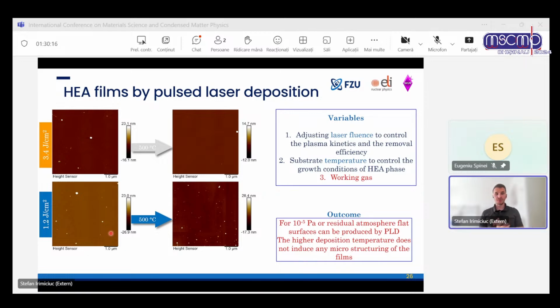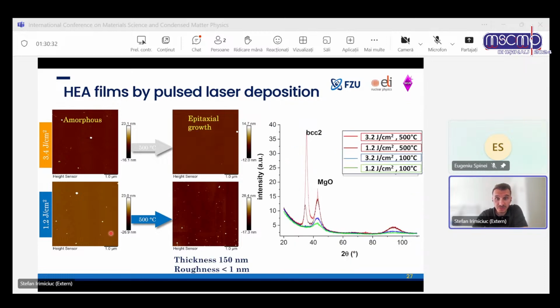So usually when you have a flat film like this with PLD, the first thing is that you made a mistake and you have no film there, because it's known that PLD gives rougher films, and we tested them, and we have these. This is how the amorphous films look, and this is how at high temperature we start to see this BCC phase, which made us believe that we are close to epitaxial growth.